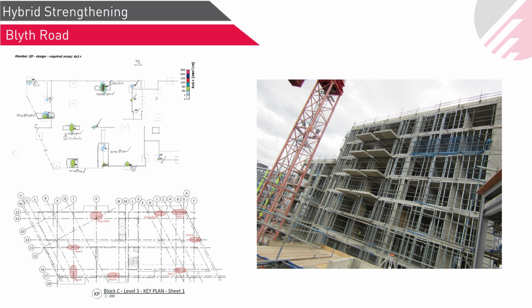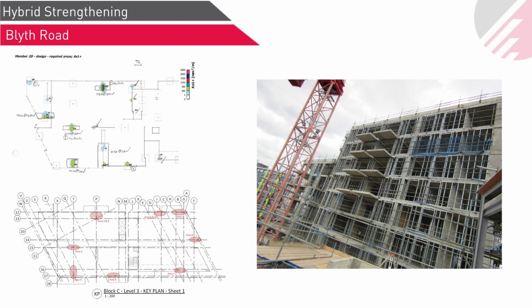So they provided us the output in terms of in what area what's missing, to what extent, and then we calculated the required amount of CFRP in those areas and developed our design drawings. So that's how the strengthening was done there. But there were some areas where the required reinforcement was very high and the carbon fiber was not viable, and also some areas where the slab was failing significantly in punching shear. In those areas, they had to use traditional steel sections as well as post-fixed shear studs for punching shear strengthening. So this strengthening was also more or less hybrid strengthening, where both steel and carbon fiber were used. But in 90% of the project, the CFRP strengthening system was used, and the remaining 10% was dealt with steel and post-fixed shear studs.